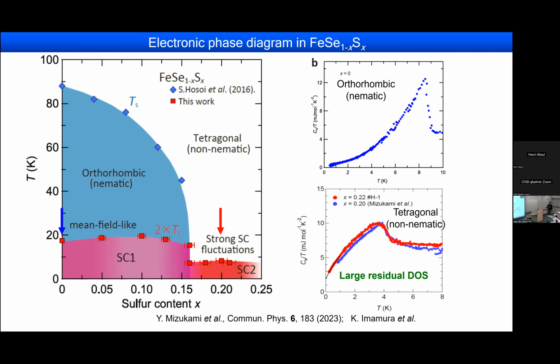Okay, and first of all, the Tc shows a kind of jump from like 9 Kelvin to 4 Kelvin. So we can say that we have 2 different superconducting states. We call SC1 inside the nematic phase and SC2 outside the nematic phase. And if you look at the temperature dependence of electronic specific heat, C over T, the temperature dependence is quite different between SC1 and SC2. In SC1, it shows a pretty normal structure. You have a jump, and the temperature dependence goes to 0. However, in the SC2 region, we have very large superconducting fluctuations above Tc, and more importantly, we have a very large residual density of states like this.